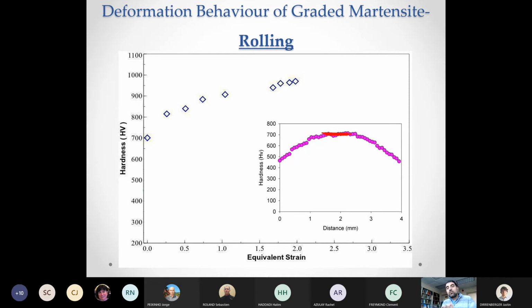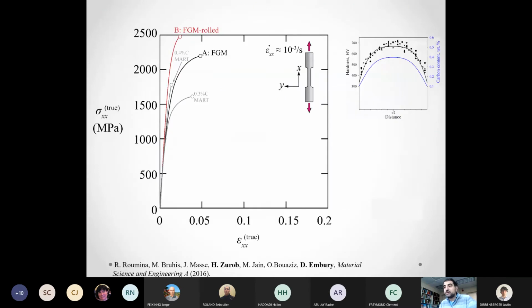And for the material to deform by such a large strain, even that inside core of the material where the carbon content is 0.4, even that region had to deform by such a large strain. So I think it changes our understanding of martensite and how martensite deforms. So martensite, even in the as-quenched state with 0.4 carbon, can support a very large strain without cracking, without fracture. And this was a very interesting point for us. We wanted to understand why and how that happens.